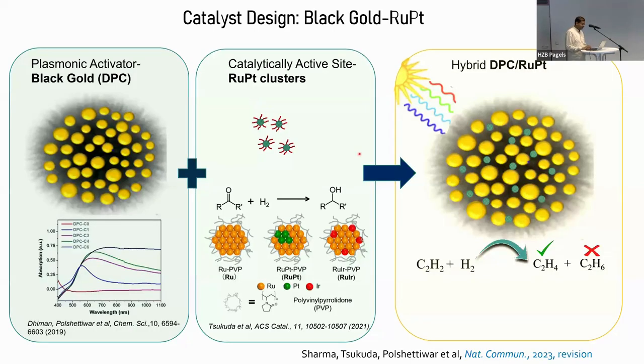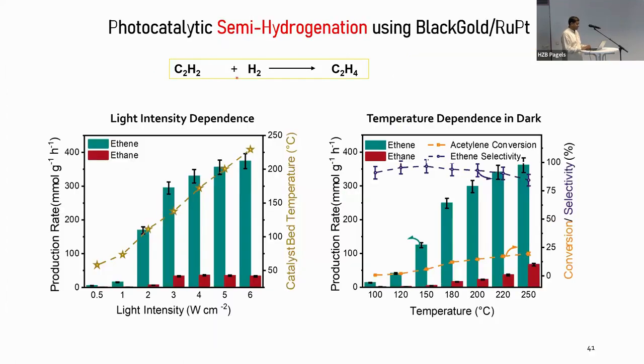So we collaborated with Professor Tsukuda for the clusters. They have very unique RuPt clusters, Pt-doped Ru clusters. And we use our black gold. We loaded the clusters onto the black gold. We wanted the cluster to remain as is, but as soon as we remove the PVP, those binders, the cluster converted into very small nanoparticles, which was still okay for carrying out this particular reaction. And then we carried out this reaction, C2H2, that is acetylene, plus hydrogen to get ethene.